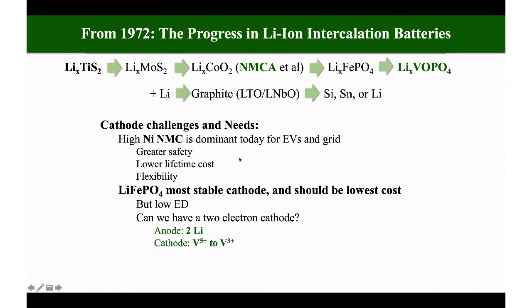So the real issues with high nickel NMC, which is dominant, we'd like greater safety. Clearly, everyone wants lower lifetime cost. And the big advantage of this system, it's flexible. So you'll find out most of the lithium ion grid storage uses NMC today in trailers. And these trailers can be moved from place to place as the utility needs them. So they can go from substation to substation and from state to state.